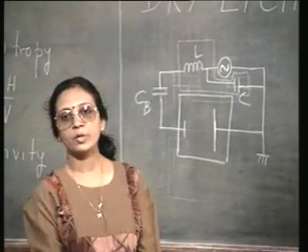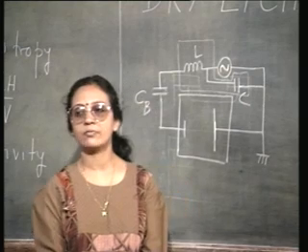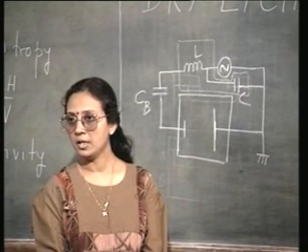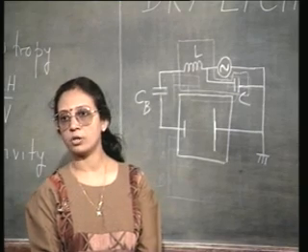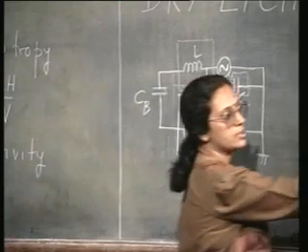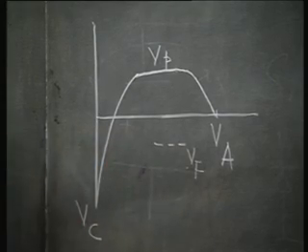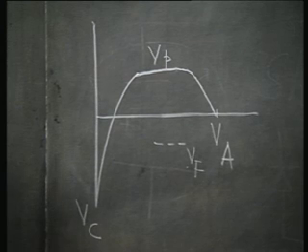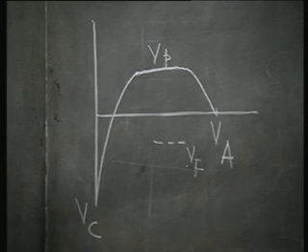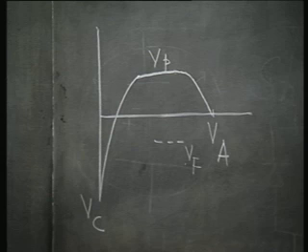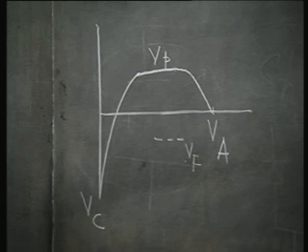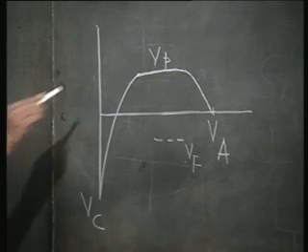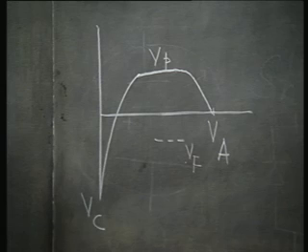If we have an insulating surface immersed in the plasma, then it is going to acquire a small negative potential which is called the floating potential. The center part of the plasma has a positive potential because it is primarily comprised of positive ions which are slow to move, and that potential is called Vp, which is a small positive potential.